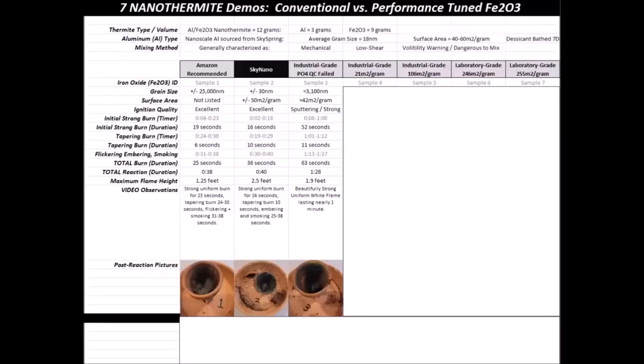The next two burn results surprised me. Both were made from our industrial grade precursor, 80% of the quality for 20% of the laboratory grade precursor cost. This sample failed our in-house phosphate aqueous absorption performance test, but it performed like a rock star in this nanothermite demo. Here we go.